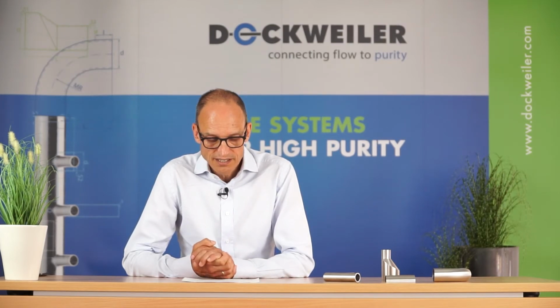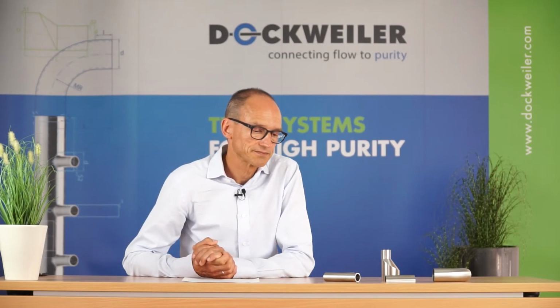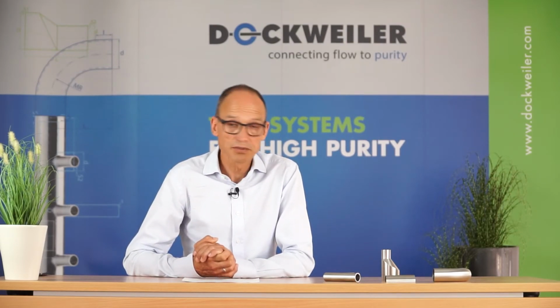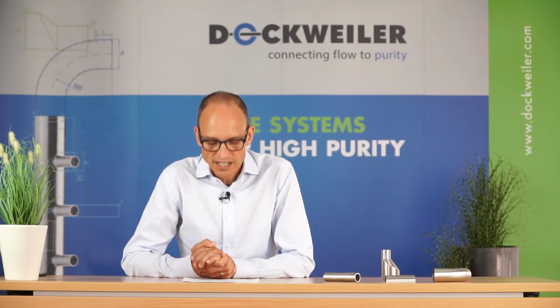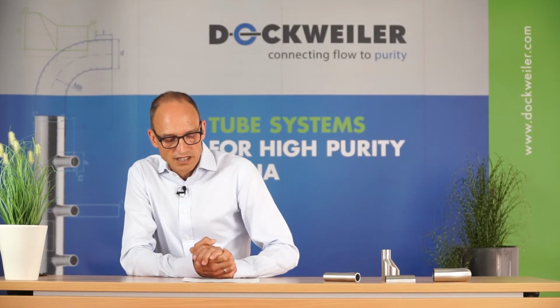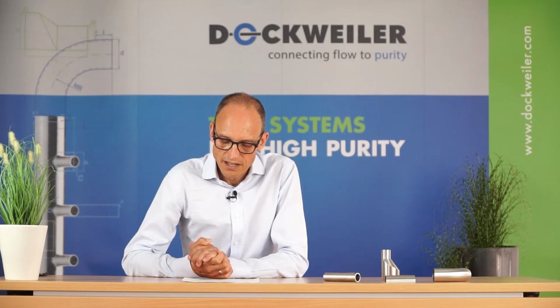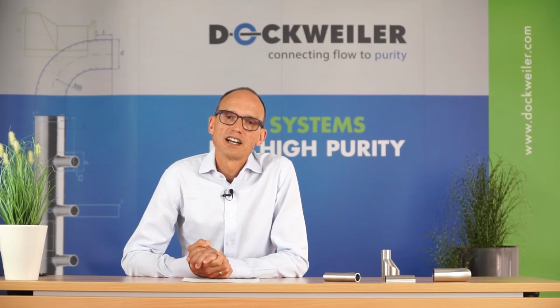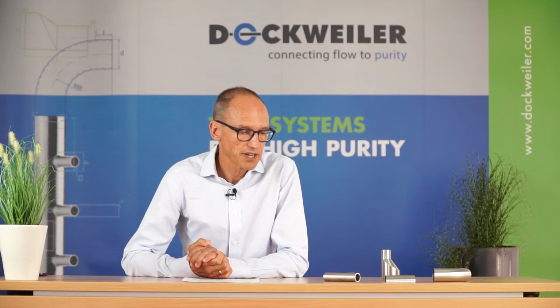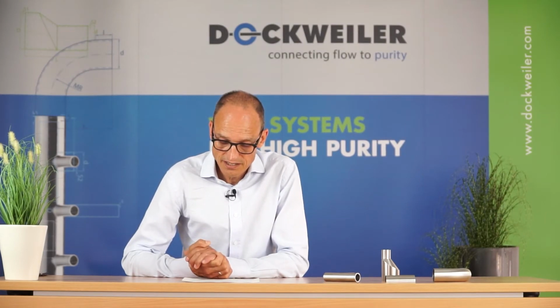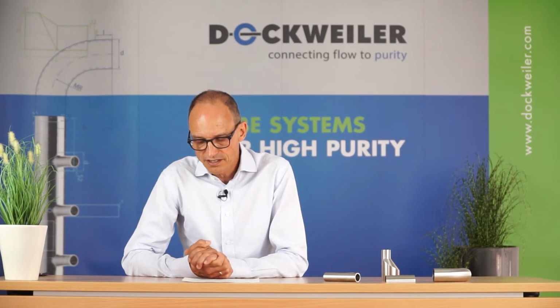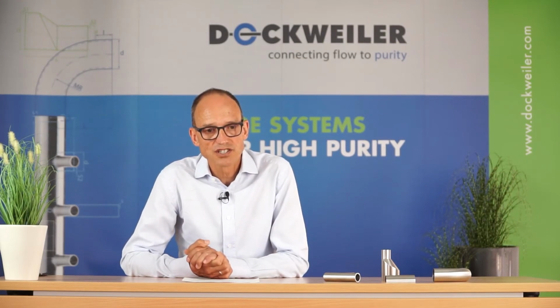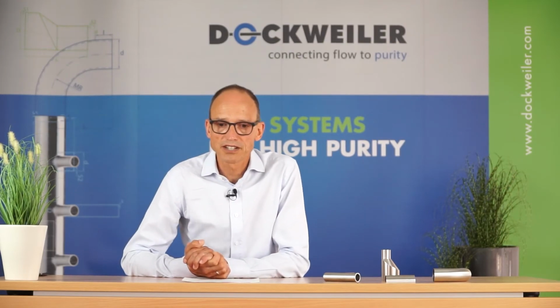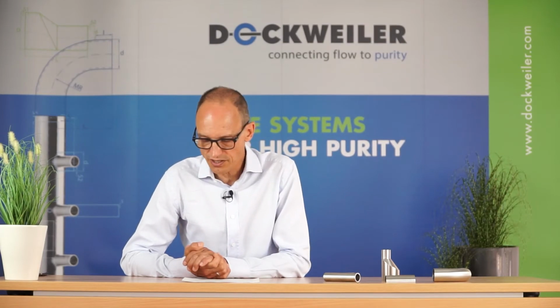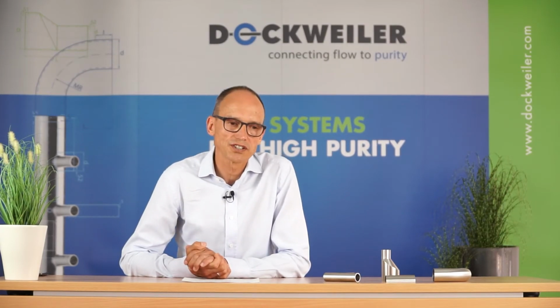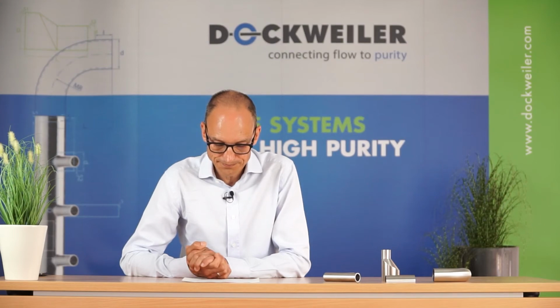Examination and inspection shall be done on a sample basis. This is also defined. So the 100% visual inspection, there is a sampling of Ra, ID, OD, dimensional check, ferrite measurement if specified. This is an option only. Marking needs to be verified. And documentation is pretty much a COC or an inspection certificate 3.1 according to EN 10204.